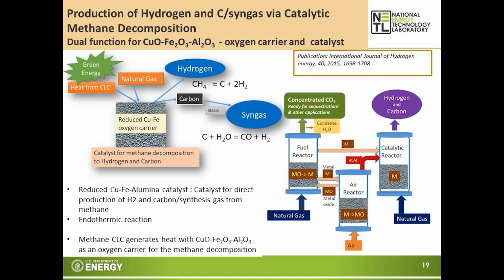The first process we have been working on is the production of hydrogen and carbon or syngas via catalytic methane decomposition. Here we use the copper, iron, aluminum oxygen carrier, which has a dual function. The oxygen carrier is used for chemical looping combustion, as I described earlier, to produce heat for the process, and the reduced oxygen carrier acts as a catalyst for methane decomposition. So the reduced copper iron oxygen carrier decomposes natural gas to hydrogen and carbon, as shown in this equation.